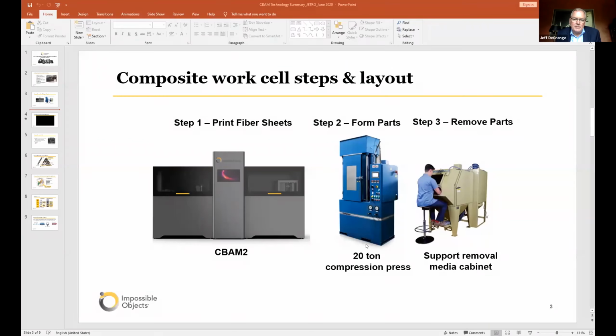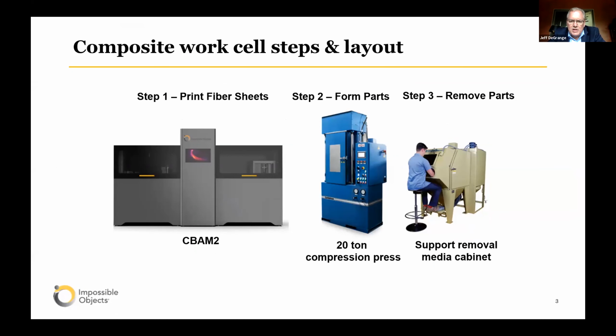The second step is that we're going to take the printed fiber sheets and then form them in a compression press, and that's where we form the parts. And then the last step is that once we actually form the parts, you have to remove the composite parts in a blast cabinet. So you need all three pieces of this equipment in order to have a composite work cell. So this is how the technology works.